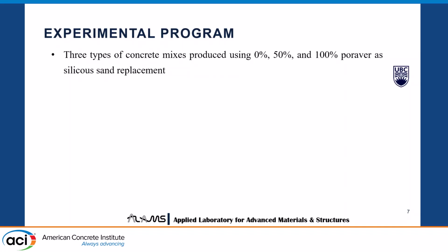And the sand that we replace is silica sand. Usually GFRC are made of silica sand. So silica sand, I guess we all know about it. It contains around 95% of silicon dioxide and usually less than 0.6% of iron oxide. On the other hand, the construction sand, the brown ones that we usually use, usually consists of up to 80% silicon dioxide. And the silica sand is made from quartz.